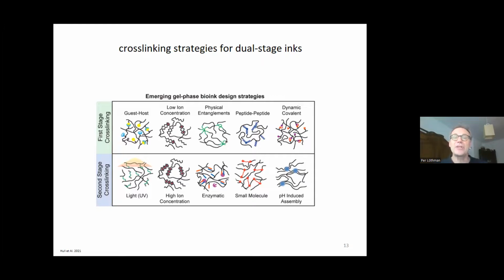Cross-linking strategy for dual stage inks. What I mean by this, what are dual stage inks? The dual stage inks are basically first stage cross-linking and second stage cross-linking, as you can see here. It means the cross-linking that can be done prior to printing, and the second stage is the cross-linking that can be accomplished after printing, and that can be, so to speak, induced via light or high ion concentration. Enzymes and small molecules and so on and so forth can support this.